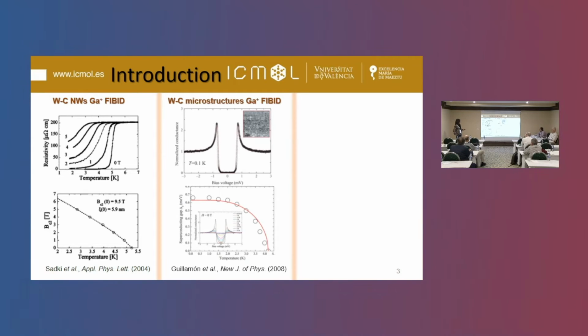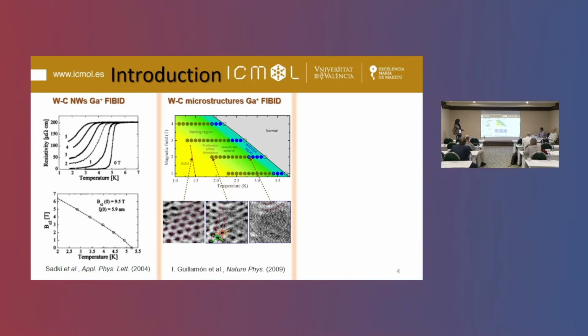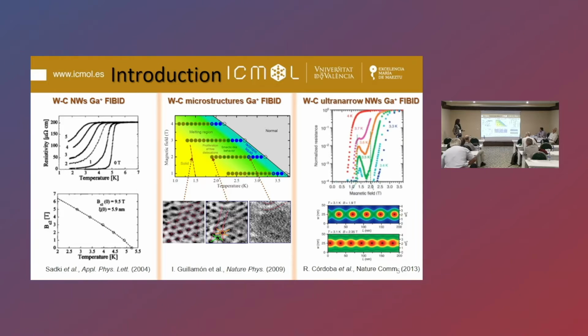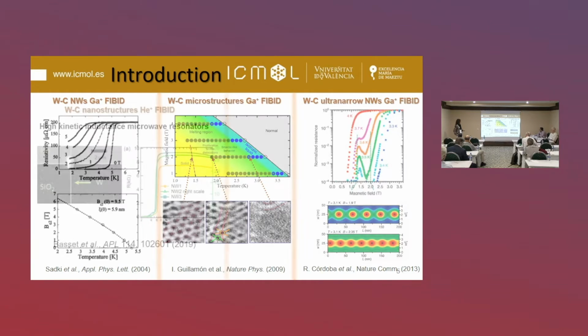Later on, in my previous group in Zaragoza, we observed that this material properly follows the BCS theory, and moreover, we observed for the first time a direct thermally dependent melting transition of 2-dimensional vortex lattices. And when the size is reduced to the nanoscale, we observe a reentrance of the superconductivity as a function of the applied magnetic field in nanowires of 50 nanometers in lateral size, due to a strong confinement of a single vortex row at the center of the nanowire.